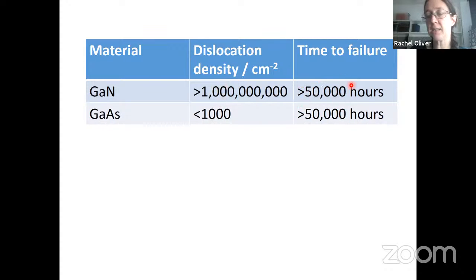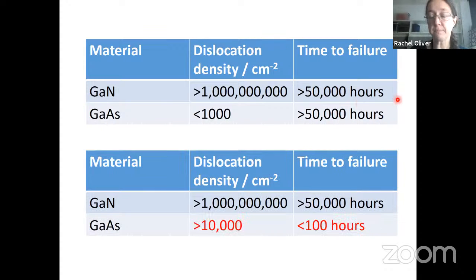And the remarkable thing is that these devices are very long-lived. Their time to failure is in excess of 50,000 hours. Now, if we were to take our gallium arsenide-based devices and increase the dislocation density by about an order of magnitude, so not up to this 1 billion per centimeter squared level, but just up to say 10,000 per centimeter squared, then the time for failure for those devices reduces from maybe 50,000 hours, 100,000 hours, down to less than 100 hours. And if you were to increase this defect density still further in your classic gallium arsenide semiconductor material, you'd expect the device to fail almost as soon as you switched it on. These devices cannot tolerate this very, very high density of defects.